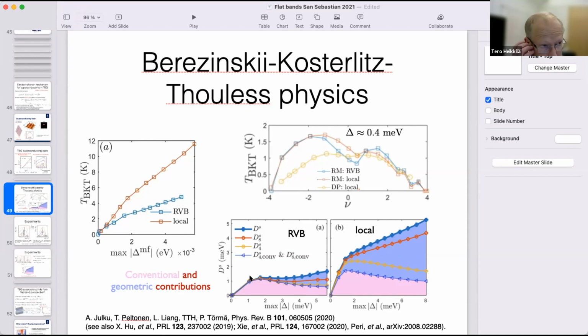And the nematic state in this case shows up in the way that this superfluid weight is anisotropic. So it is a matrix. You apply a phase gradient in one direction and you get a finite supercurrent also in the perpendicular direction. And this would be a way to measure this nematicity.